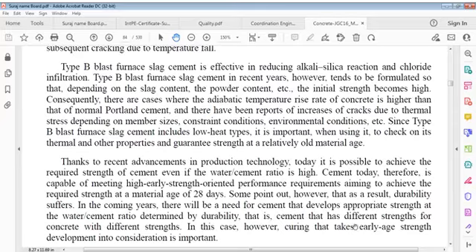So type B blast furnace slag cement is effective in reducing alkali silica reaction and chloride infiltration. Type B blast furnace slag cement, however, tends to be formulated so that, depending on slag content and powder content, initial strength becomes high. Consequently, there are cases where the adiabatic temperature rise rate of concrete is higher.